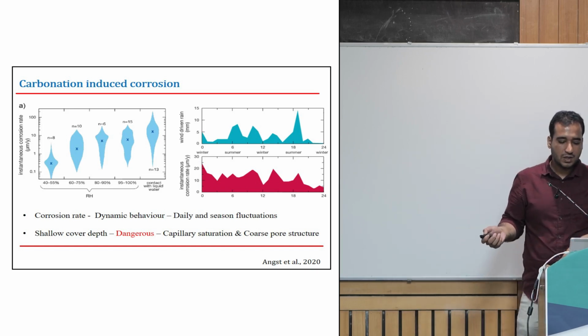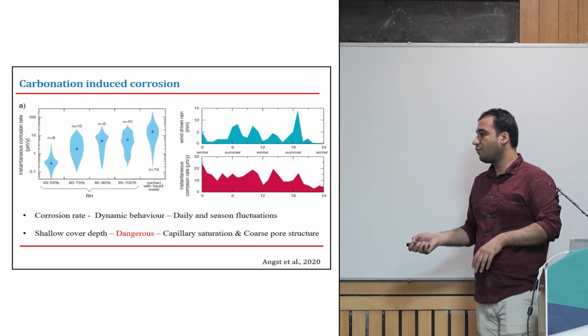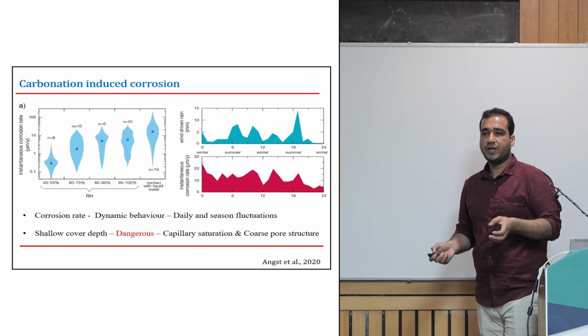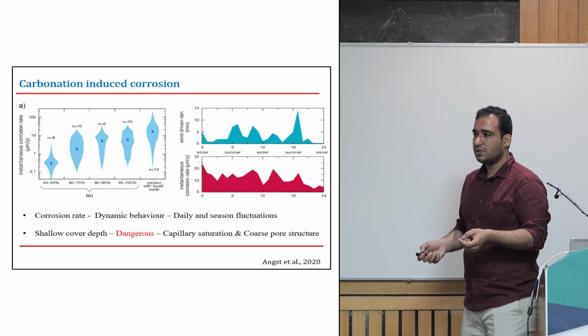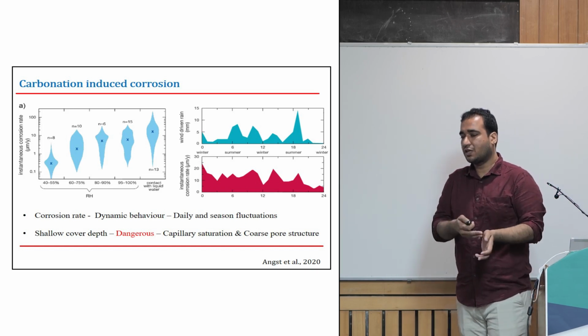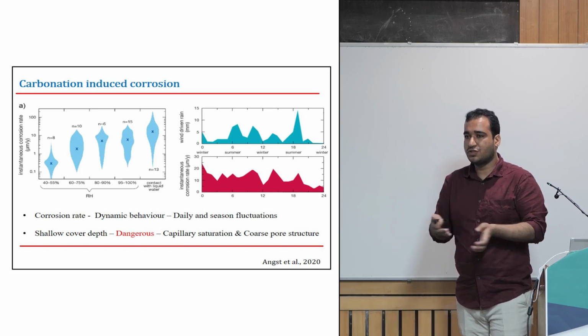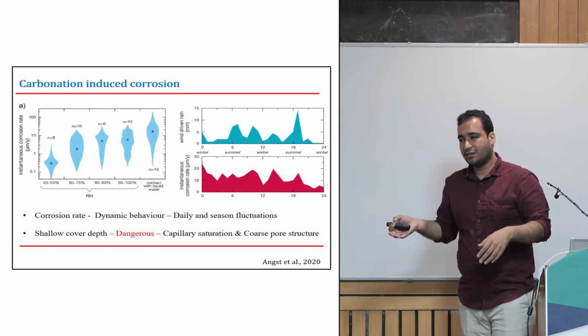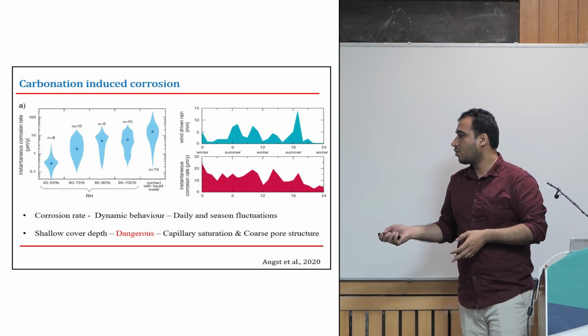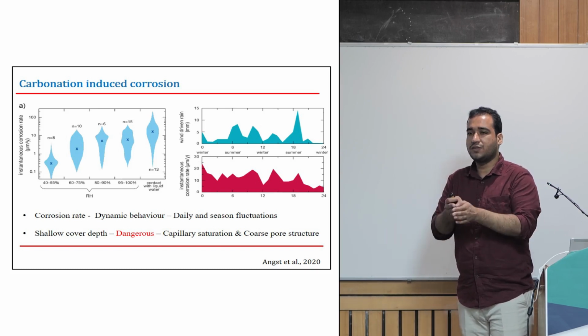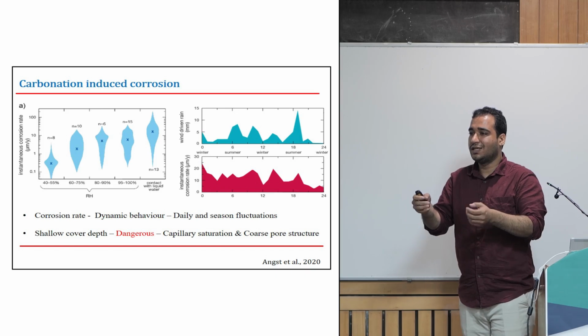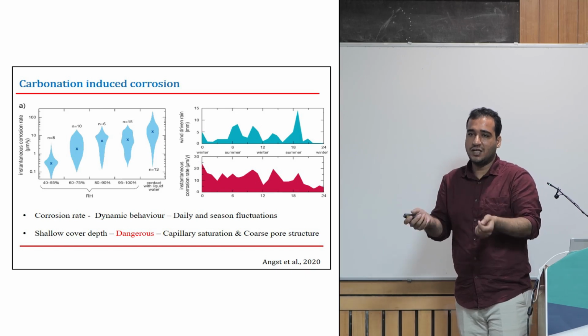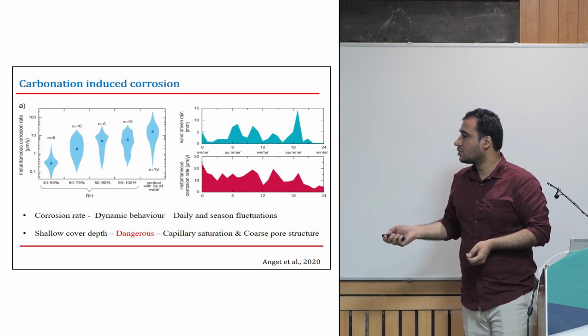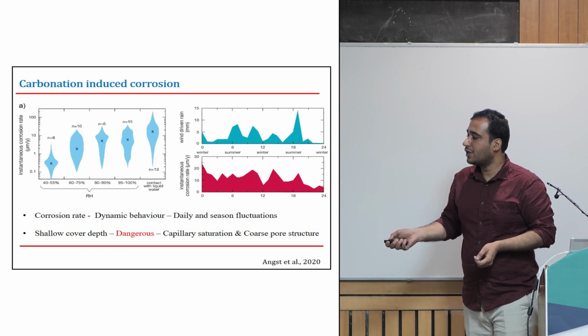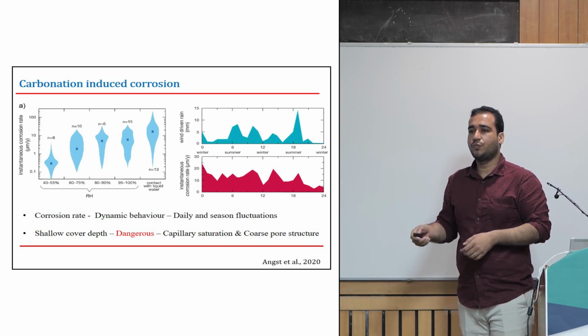Another thing is, in terms of carbonation, what's more dangerous is shallow cover depths. If you don't provide adequate cover depth, there is quite less time to saturation. You splash it and it directly gets saturated, and you get a coarse pore structure because the cover depth is less, and aggregates were not able to get there. It's kind of a cement paste and finer aggregates only. So you get a coarse structure. These kinds of situations are more critical in terms of carbonation rather than when you provide sufficient cover depths.